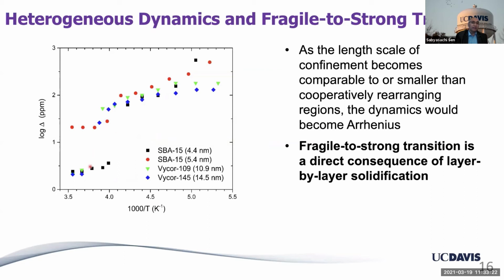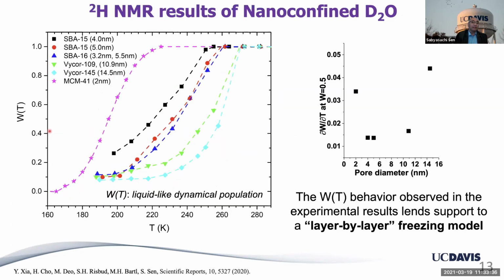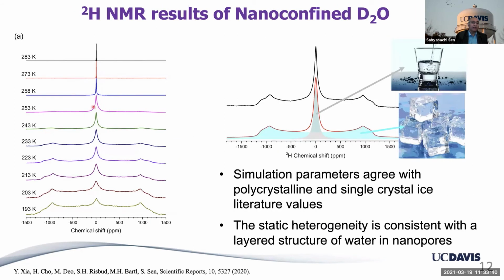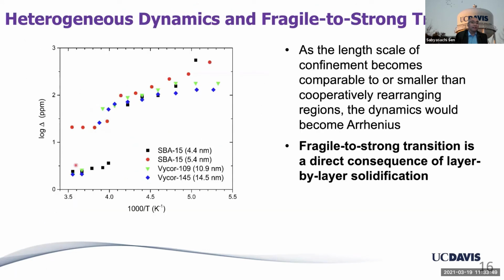And this heterogeneous dynamics is something we have seen also once we plot the logarithm of the line width as a function of reciprocal temperature. This line width is the width of this liquid-like line here in the deuterium NMR spectrum. The line width is related to how fast or slow the water molecules are moving. And you can see that below a certain temperature, in each case, the line width shows a fairly nonlinear, sort of sudden jump, indicating that as water gets more and more confined upon freezing, it becomes more and more rigid in its dynamics and slow. And this kind of slow dynamics comes in because of its self-confinement as the layers of ice around it grow.